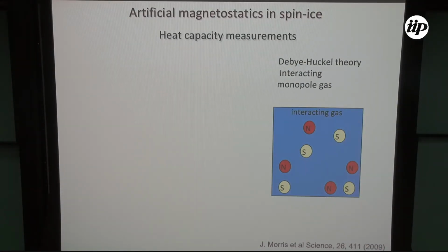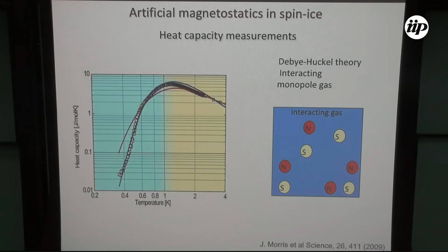So the first way in which you can check whether this picture is good for the experiment or if it's complete nonsense is by doing this. You say, okay, if I have my sample and it's at a low temperature, what I expect is that my excitations would be pairs of these charges. And now, this is one of the beautiful things about this picture, I can take all the results I knew from electromagnetism and use them for this sample. So I can use the Debye-Hückel theory and calculate what will be the specific heat I expect for some density of charges, and this is what you get.